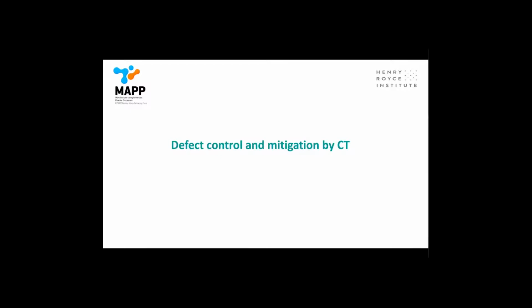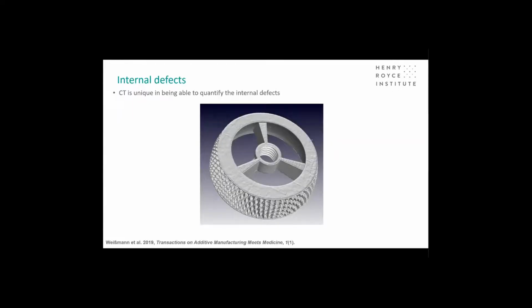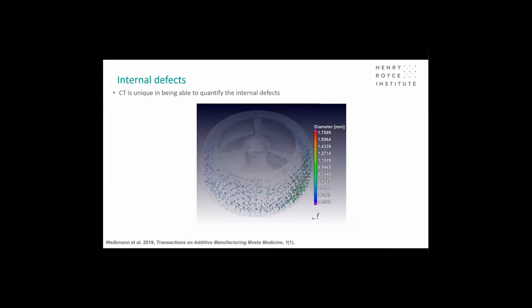But I want to focus more on the defect control and mitigation by CT. We talked already about the potential for cracking. I'm going to focus more on internal defects, but obviously cracking can also be studied by CT. And the key point is that as well as measuring the external geometry with a CT scanner, you can get a picture of the internal defects, and you can get the population of defects, both in terms of their size, their shape, and their location.